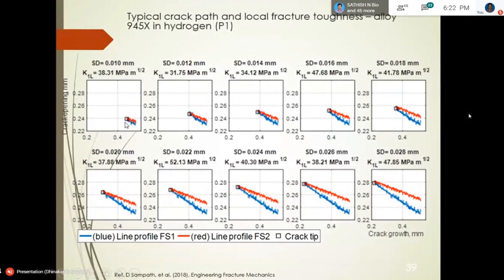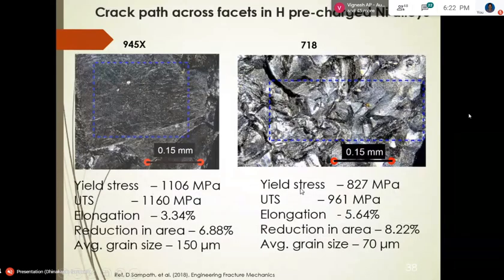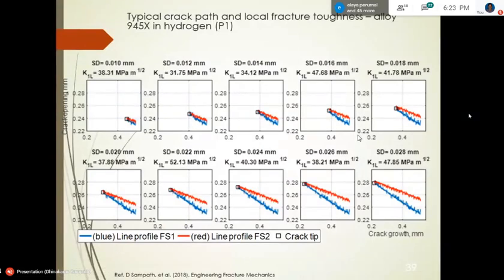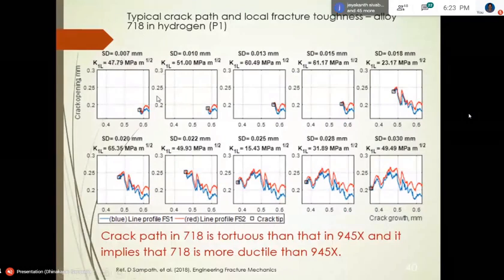And these are the cross-sectional plots where we see that the crack is growing. This line analysis shows the crack opening when one surface is moved with respect to the other, and I also plotted the local fracture toughness for each separation distance. When we did this for the entire surface area of 945X and 718, we get some kind of normal distribution. We'll see that in a minute. For 945X we saw a very sharp crack, and for 718 we saw a tortuous crack. That means we have a lot of resistance to crack growth, because the load applied will be consumed in the interaction between the surface, the crack wake.